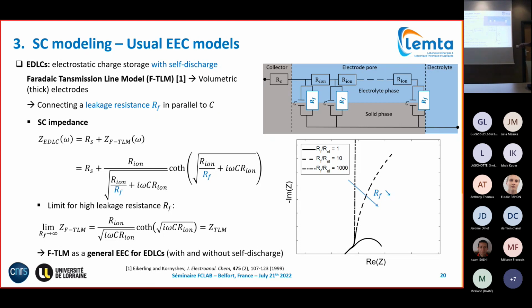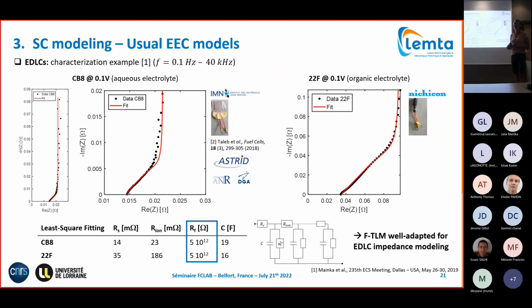And if you have really high leakage, you will end up with a small loop at low frequencies. So this parallel connection of the leakage resistance to the capacitances is the typical way to take into account Faradaic reactions. We call it the Faradaic transmission line model. And you can show that if this leakage resistance tends to infinity, meaning negligible leakage, we end up again with the vertical line at low frequencies, which is the case of ideal EDLCs. So this Faradaic TLM can be used as a general circuit for all kinds of EDLCs with and without self-discharge. And we tested that by characterizing different kinds of EDLCs.